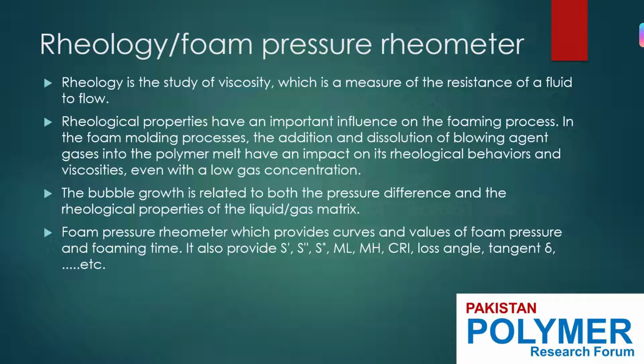Moving ahead, since the rheological property is closely related to the polymeric forming, it is important to measure the viscoelastic properties of polymer so as to provide a quantitative guide to help control polymer forming. Commercial rheometers such as an oscillating rheometer, elongation rheometer, capillary rheometer, and the foam pressure rheometer are widely used to measure the polymer viscosity data.